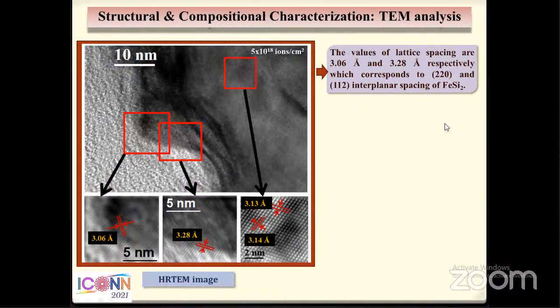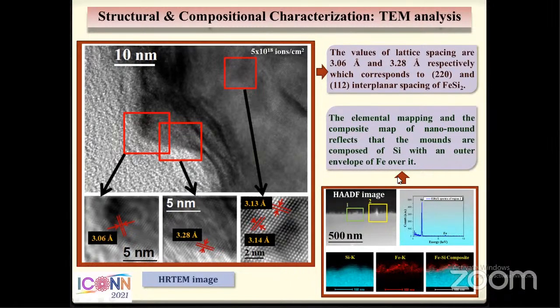Also, we have observed the TEM analysis, and from the TEM analysis also, the presence of the silicide bond can be clearly observed. Here the lattice spacing corresponds to the interplanar spacing of iron silicide, and also from the high angle annular dark field image, we observed the presence of iron silicide in the ripples. And also here we can see that the ripples are composed of silicon, but there is a layer of iron over the silicon surface.